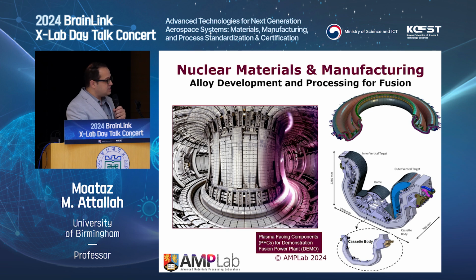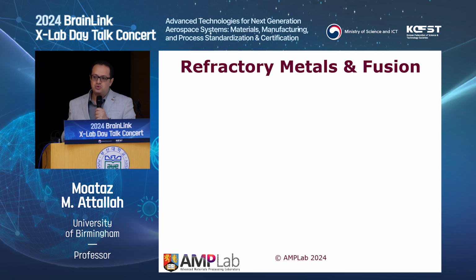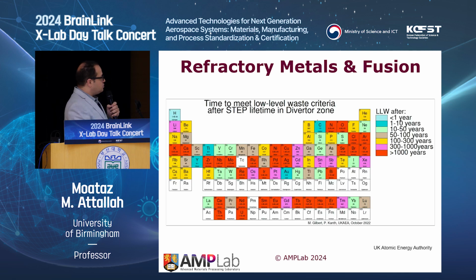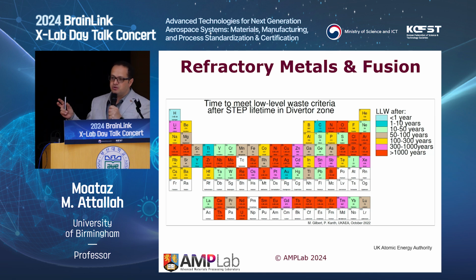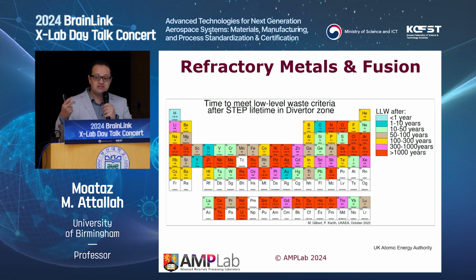These walls are typically made out of tungsten or vanadium or some steels. And we need to find a material that can protect from the interaction with the plasma around it. The choice of material is limited. So it's tungsten, as I mentioned. And the reason for that is if you talk to people who do nuclear fusion, the first thing they show you is the periodic table. And they tell you, we don't want that, we don't want that, we don't want that. And then eventually you get to the point where we can be happy to live with tungsten or tantalum and chromium and vanadium, a very limited number of elements in the entire periodic table, mainly because of the activation of these materials.